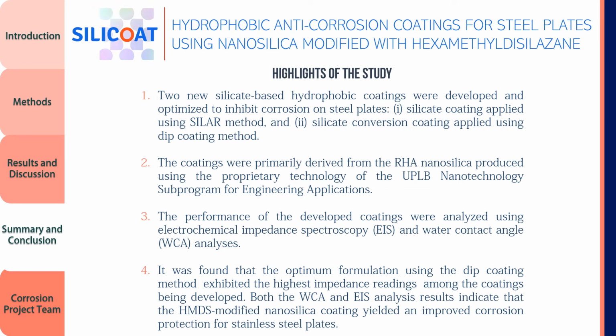It was found out that the optimum formulation using the dip coating method exhibited the highest impedance readings among the coatings being developed. Both the WCA and EIS analysis results indicate that the HMDS modified nanosilica coating yielded an improved corrosion protection for stainless steel plates.